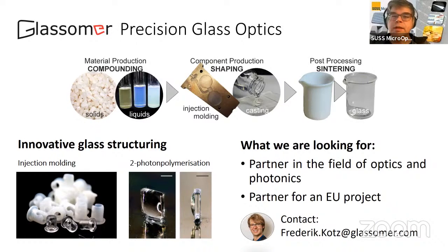Thank you for calling up, Jose. I wonder, what is the shrinkage typically of these materials? So when you have a mold, first of all, it has to demold easily. That's more the chemical situation. And then the other thing is, when you have shrinkage, you have to do a lot of form compensation beforehand. The materials we use in our imprint process typically have low shrinkage, but form compensation can already be challenging. If you have more than 5 or 10%, it might be very challenging to pre-compensate those shapes in a single iteration. Just wonder what your experience is.